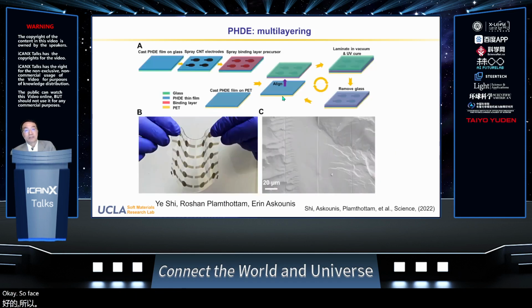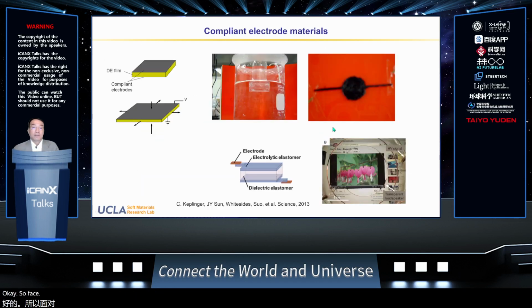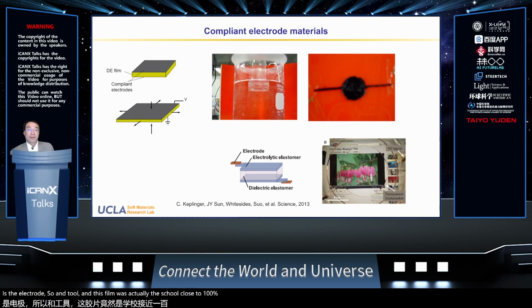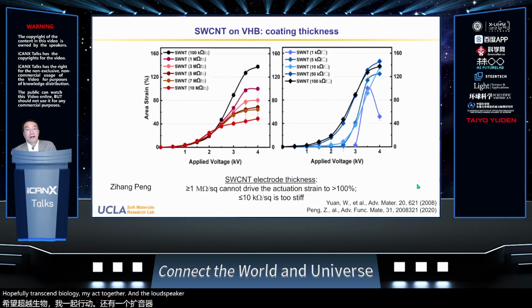Sorry about that. So the salt water here is the electrode, and this film actually reached close to 100% in area expansion. The lower images are from the work of Christoph Keplinger, et al. at Harvard. They showed that you can use a gel electrolyte as the electrode, and the gel electrolyte is transparent. So you can have a totally transparent dielectric elastomer actuator and a loudspeaker for this system.